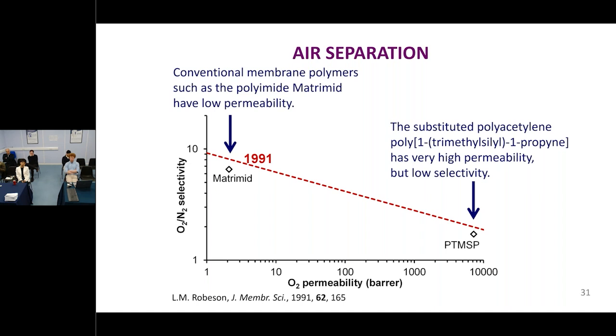It's one where we'd very much like to get higher selectivity to open up a whole new range of applications, particularly applications where you want high oxygen content rather than throwing away the oxygen. But this sort of illustrates the point. So that red dashed line is where the situation was in 1991. And there are many points that Robeson looked at. I've just pointed out a polyimide, which is often used for these types of membranes, Matrimid, because it has a reasonable selectivity, but its permeability is pretty low. And there were a few polymers with very high permeability, in particular a substituted polyacetylene known as poly(1-trimethylsilyl-1-propyne), PTMSP, very permeable, but not very selective.